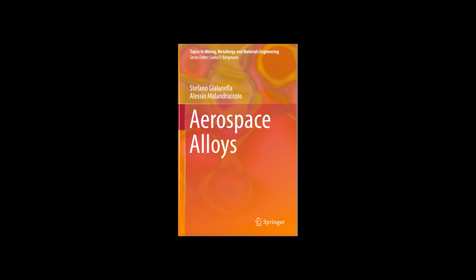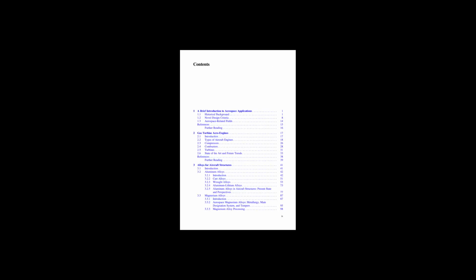It's actually often the intermediate, sort of unstable structures that give the most strength. Huh. So not necessarily the final, most stable form. Often not, no. Like in a common alloy like 6063, that's aluminum with magnesium and silicon, you get these beta prime precipitates. They actually line themselves up in specific directions within the aluminum crystal lattice. Why do they do that? It's energetically favorable. It's like they fit better that way.